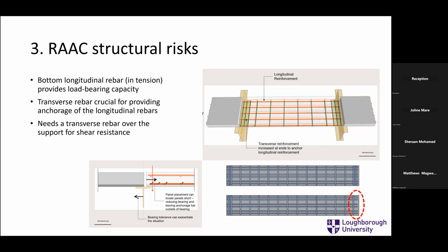So the guidance says that last transverse bar, anchorage bar, needs to be over the bearing. Because if it's not, then you've got no reinforcement at the edge of that bearing. And a shear crack can develop from the edge of that bearing into the plank. And that's a shear crack with no warning. There's no deflection warning. There's no initial cracking. It just cracks, a shear crack, and it can collapse. And that's what it looks like has happened in some of the failures.